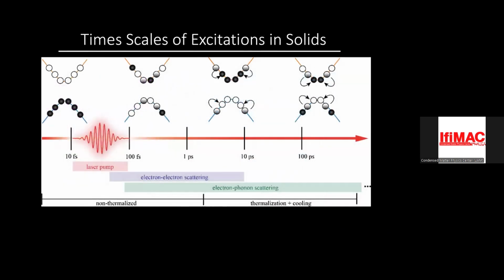So let's talk about time scales in solids. Let's just take a very simple example. Supposing you have an insulator, and this is the ground state. You shine a pulse of laser light, the first thing that happens is electrons get excited from the valence band into the conduction band. And then the question is, what happens and over what time scales? The first thing that happens is that you have electron-electron scattering, and that happens really quickly, within a few femtoseconds. And that causes some of these electrons from the higher energy levels to go back to the valence band. But then over longer time scales of picoseconds,